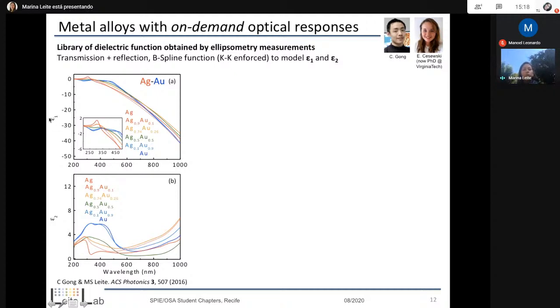And here, what I'm showing to you is epsilon 1 and epsilon 2 as a function of wavelength. And it's color coded, right? So what is striking here is the fact that for epsilon 2, for instance, we do have for 50-50% gold silver a quite different response compared to the other metallic mixtures that are more in the red, the yellowish color here, that are silver rich.